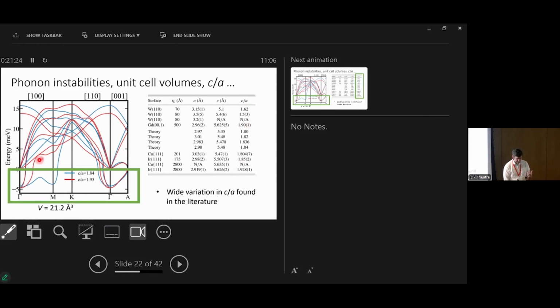And this part down here, these negative energies, are instabilities, theoretically predicted instabilities. And you can see that the position of these instabilities in momentum space is varying depending on the lattice parameters, specifically the C/A ratio. That's a technical detail. But those positions vary with the lattice parameters that we have. And those lattice parameters actually turn out to be thickness dependent as well. So that was giving us the hint as to what was going on.